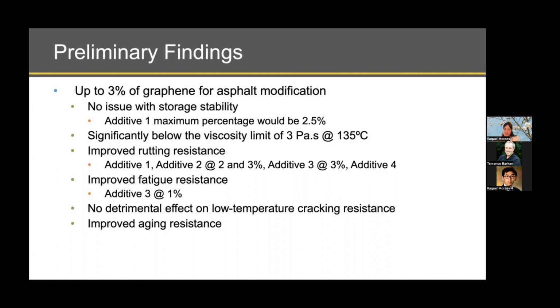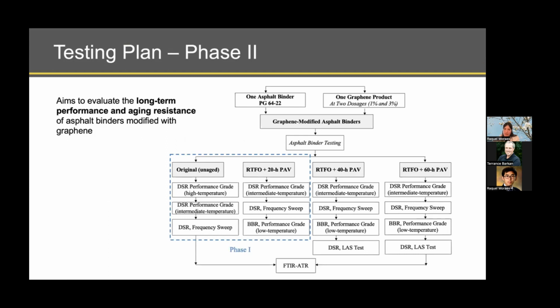And when considering the Glover-Rowe parameter results after 20 hours of PAV aging, we saw that the graphene products improved the aging resistance of the base binder. With that in mind, and as it was indicated in the beginning of the presentation, the results for us were very positive in the sense that, first, from the literature, we saw that before performing this specific study, we did a literature review to understand a little more of the material.